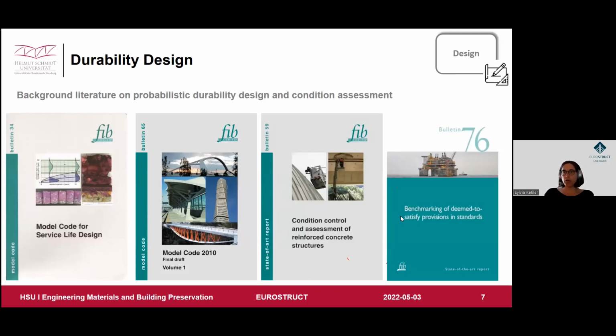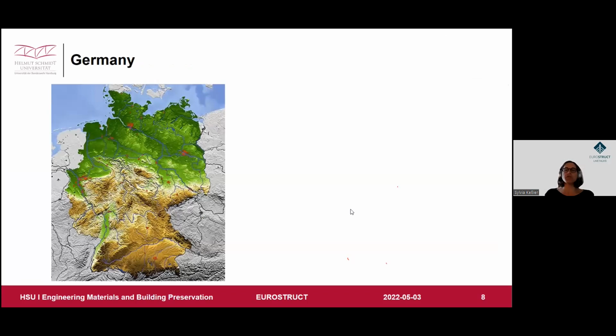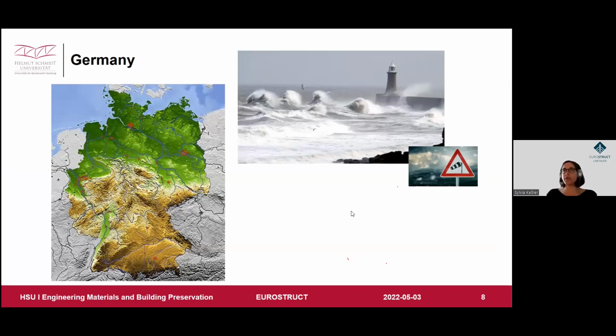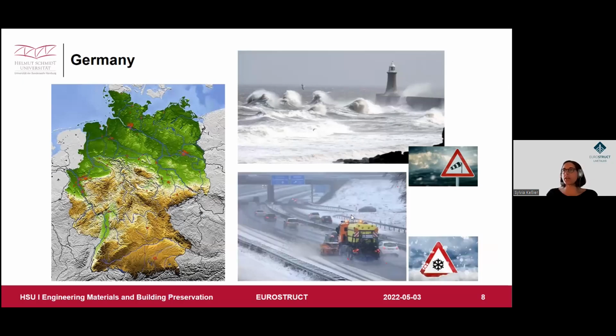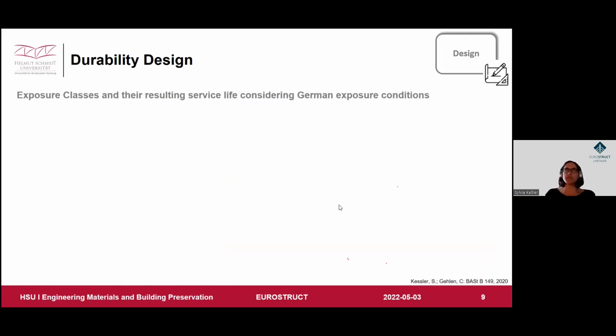We had a project going on in Germany, and we would like to consider what are really the exposure conditions we have in Germany. In the northern part, we have the seas, the marine environment, so here we really have to be concerned about chloride-induced corrosion. And in the south, we have a lot of snow, harsh winter times, and here a lot of de-icing salts are applied on the streets to ensure traffic safety. We looked at what the typical stresses are with regard to corrosion, and we compared this to the material resistances which are allowed according to the Eurocode. And the result was kind of surprising.